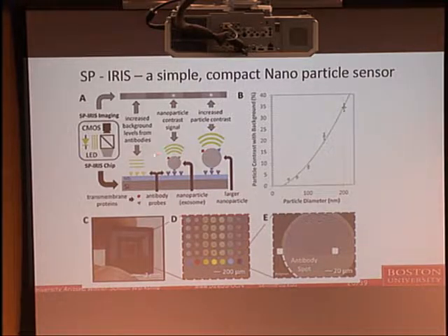So the scattering is interfering with this, and you can see it. And not only can you see it, it also relates to the size of the particle, so you can also determine the size of the particle by doing this measurement. We're not beating the diffraction limit. These particles are sparse on the surface. They're far apart from one another, maybe a particle at most at each micron spacing. But they're invisible if you do not use this reflecting surface.